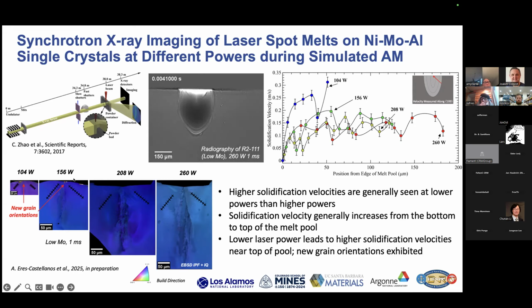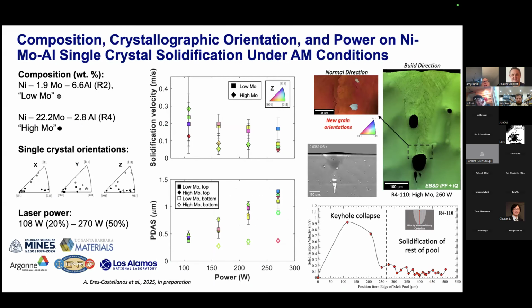And then for the lower power conditions, you see some new grain orientations at the tops of the melt pools where the higher velocities are experienced. And this kind of summarizes some of those results. So a couple different compositions, a bunch of different orientations, different power conditions. And I've already sort of talked about velocity versus power. But again, we can look at characteristics of the microstructure.